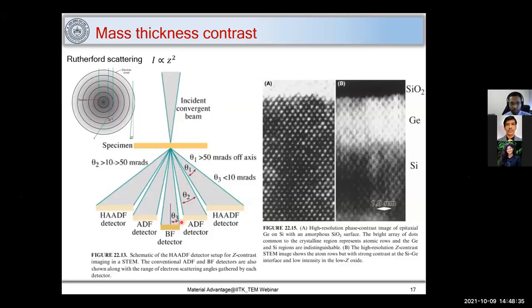That is done by the ADF, that is the annular dark field detector, or HAADF, that is the high angle annular dark field detector. These are nothing but annular detectors. That means these are discs with some gap in them. So this is what the openings in the discs are. That is why they are called annular detectors. High angle means they are at high angles, and thus they are called high angle annular dark field.